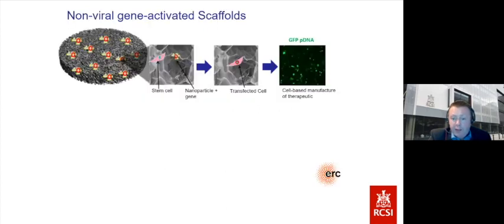So to achieve that, what we have to have are nanoparticles embedded in the scaffold matrix. So you've got the same porous implant as before, except you've now got a nanoparticle. That nanoparticle is complexed with your nucleic acid, so the gene of interest. And when the cells move into this porous implant, and that's what I should say, because it's biomimetic, the cells in the body, in the defect site, move through the porous implant, they grow into it, they populate it, but now they take up those nanoparticles through endocytosis, and then they begin to overexpress that protein.